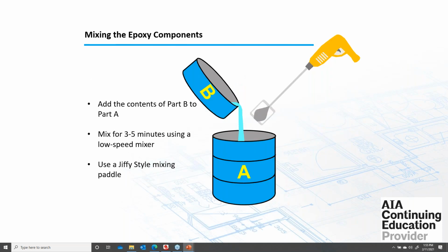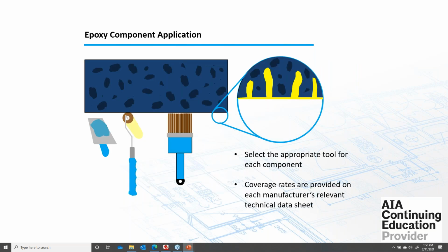Next slide. When mixing the epoxy components, always try to add the part B to the part A. Mix for at least 3 minutes using a low-speed mixer, and ideally use a Jiffy style mixing paddle for most of the epoxies. Next slide. Also select the appropriate tool for each component to apply it. So for example, the primer, which is very fluid, can be applied using a paint roller, and the epoxy putty, which is much thicker, will require a trowel or a spatula. Coverage rates obviously are provided on each relevant technical data sheet.